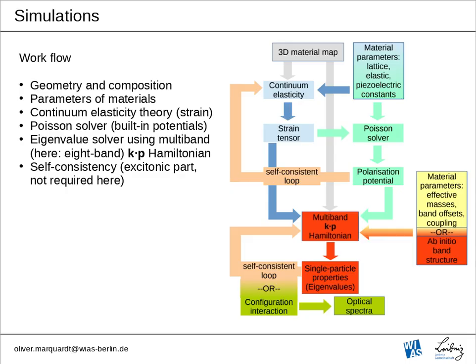This shows you the workflow of such a simulation. So first of all, you start by defining the geometry and the composition of your heterostructure in a 3D material map, which is pretty much a simple ASCII file. Next, you define the parameters of all materials involved, which for the first step would be lattice, elastic, and piezoelectric constants, and later on effective masses, band offsets, and band couplings for the electronic properties.